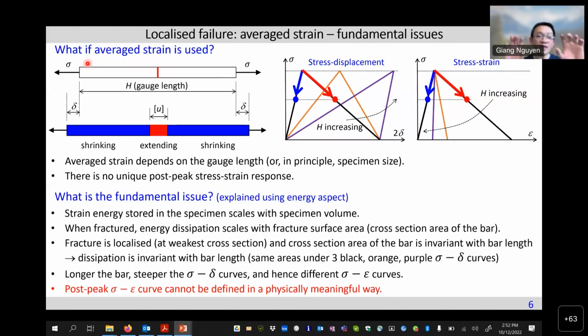Okay, so due to that scaling, the energy dissipated scales with the surface area, but the energy storage scales with the volume. So these are very different. So fracture in this case is localized, and it happens at the weakest cross section, like a spring. You break it at one specific point, that is the weakest. So in this case, if we do it the traditional way, we ignore the energy dissipation, and we end up having just stress strain. They're totally incorrect. And the stress strain curve in this case for post peak or post localization, everything localizing, is not correct physically.